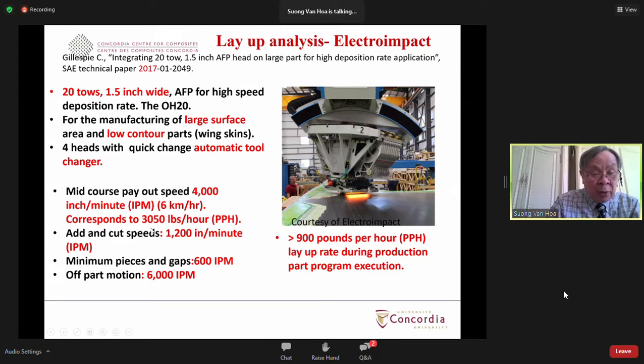So that is a fast speed. If you have to add and cut, it goes down to 1,200 inches per minute. And the minimum gap, we have 600. Off part motion, 6,000. So out of all these different times here, the average amount of material deposited is about 900 pounds per hour.